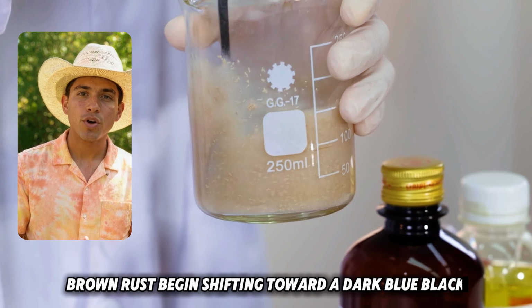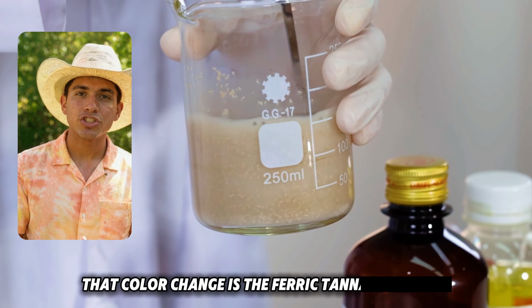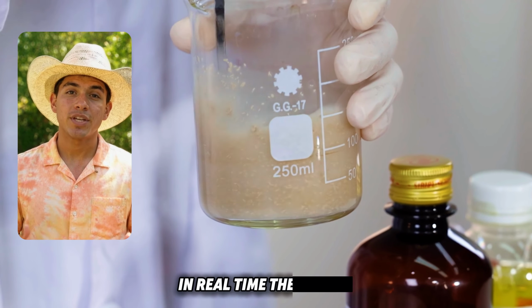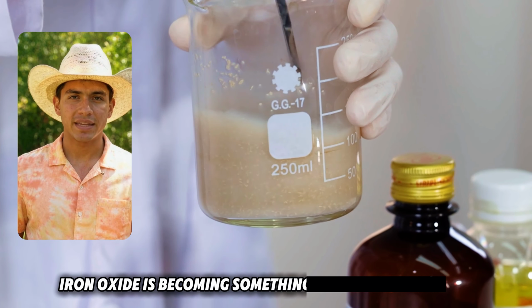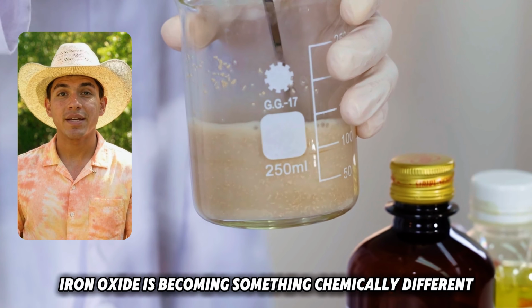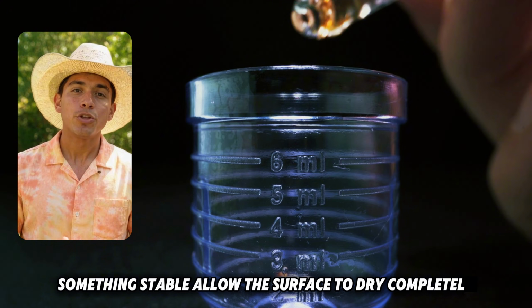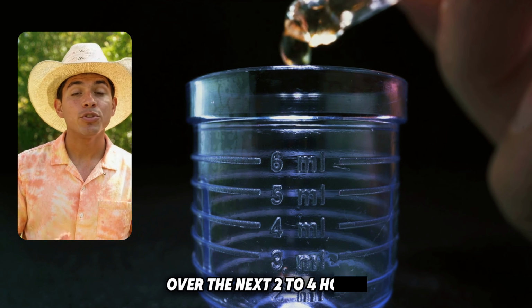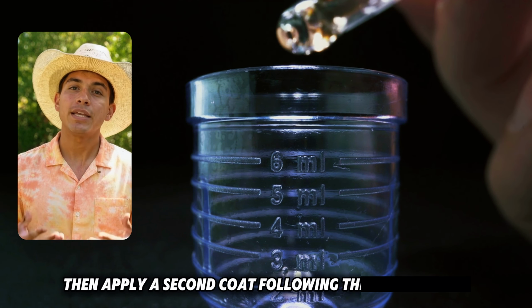Within 10 to 15 minutes, you will observe a visible color change on the treated surface as the orange-brown rust begins shifting toward a dark blue-black. That color change is the ferric tannate forming in real time. The orange iron oxide is becoming something chemically different, something stable. Allow the surface to dry completely over the next 2 to 4 hours, then apply a second coat following the same process.